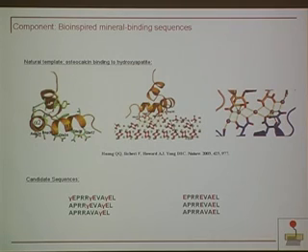Gamma E residues are carboxyglutamate residues. So GLA, gamma E, and carboxyglutamate all mean the same thing. I'll try not to use them interchangeably. I'll just call them carboxyglutamate residues. Then we mutate these residues either to native glutamate, which contains 1 less carboxylate group, or to alanine, which contains no carboxylate groups. Our hypothesis was that we could change the interaction between these peptides and the surface of hydroxyapatite.